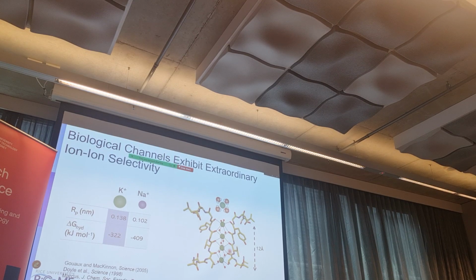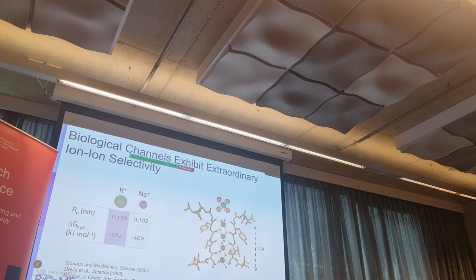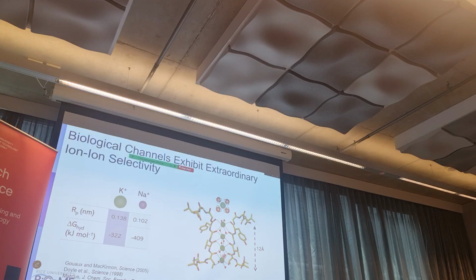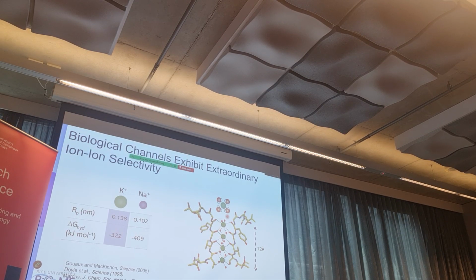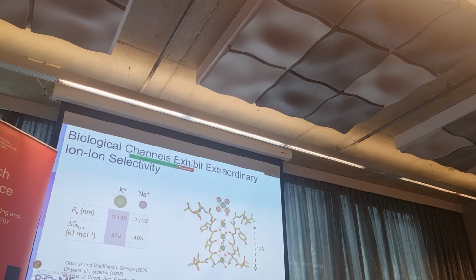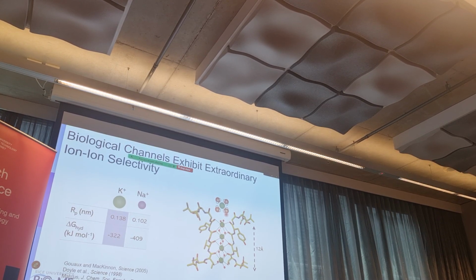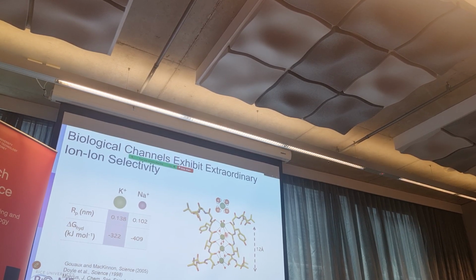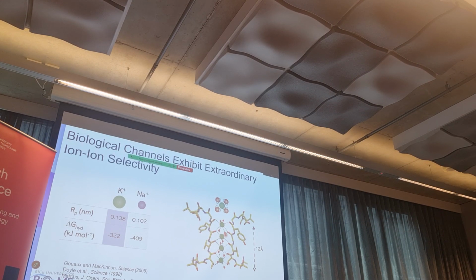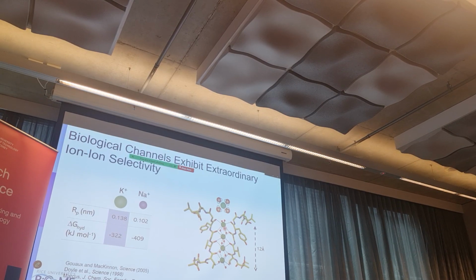And it's a very narrow pore size, the right size, and also the right functional groups. So what's happening there, when the potassium comes here, it's hydrated, and it becomes completely dehydrated. When it is completely dehydrated, it's unstable, but it binds to this oxygen-containing group, and now the potassium feels exactly like there are some water molecules around it. As opposed to the sodium, which doesn't fit in the size and cannot coordinate here, so it doesn't follow this mechanism.